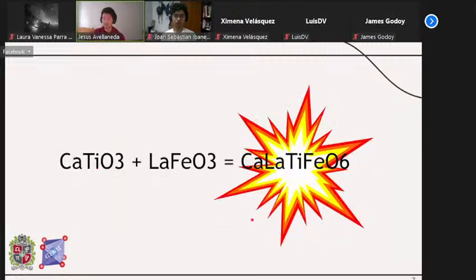Throwing the formalities out of the window for a sec, if we write down a little stoichiometric equation and operate the whole thing up, apparently, at first glance, these structures can lead to a new one. The sample CaLaTiFeO6. First of all, initial calculation using the SPuDS software showed us that we had a high enough tolerance factor around 0.95 for two specific structures.